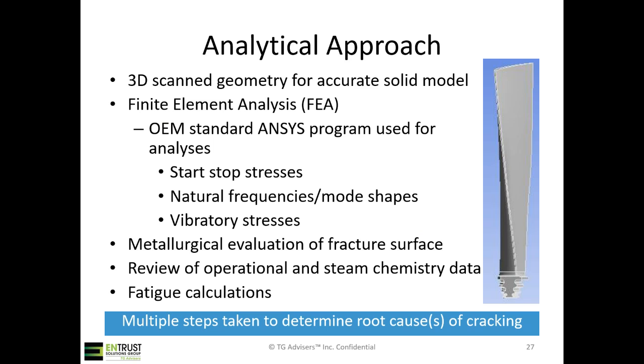Then we used a finite element analysis software, ANSYS, which is an OEM standard program used widely throughout the industry to assess stress due to stop-starts and steady state operation. As I mentioned, look at those natural frequencies and mode shapes, and then look at the vibratory stresses as well. We also performed a metallurgical evaluation of the fracture surface through a lab that we partner with, and then reviewed operational and steam chemistry data to look for any clues to anything that might have potentially contributed to the cracking seen here if the unit was operated improperly, and then lastly performed fatigue calculations.